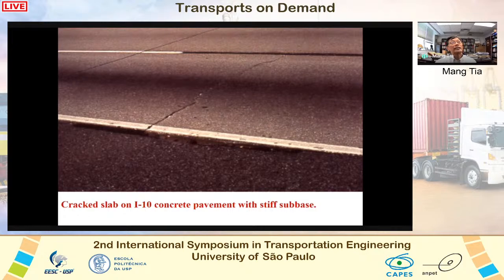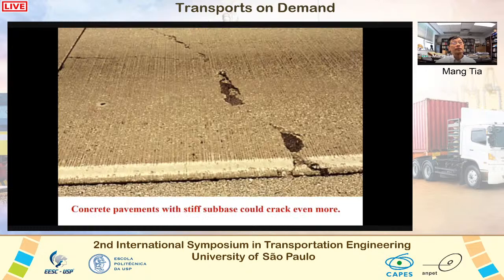So using a stiff subbase would not help in reducing cracking in the pavement slabs. Here's an example of a cracked slab on a pavement with a stiff subbase. And concrete pavement with stiff subbase could crack even more, as we have seen from our observation.